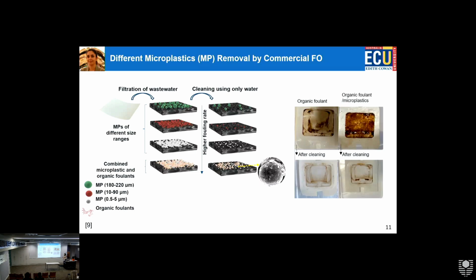So with forward osmosis, we expect that we can clean the membranes much easier. So after cleaning, we see that both of them have almost retrieved their properties, but it would be much worse after cycles in this case, because it needs to remove more foulants over the course of many years if it's in the actual plant.